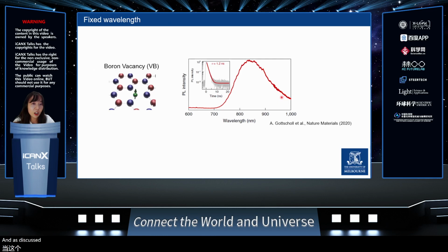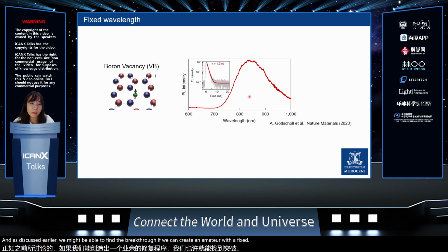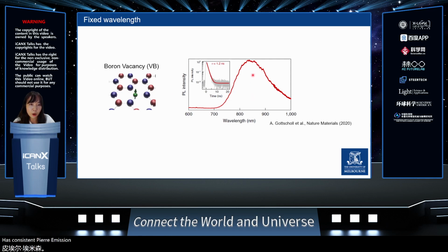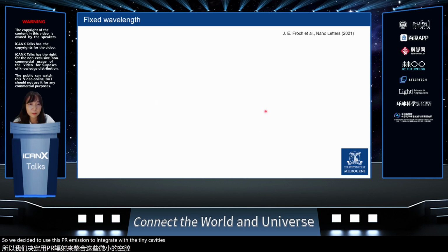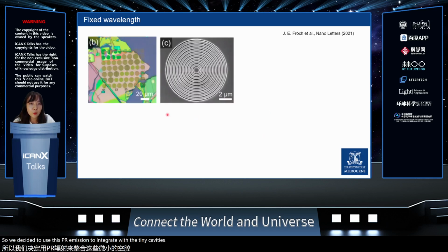As discussed earlier, we might find a breakthrough if we can create an emitter with a fixed wavelength. One of the discoveries in 2020 is that the boron vacancy in hBN has consistent PL emission around 800 nanometers. So we decided to use this PL emission to integrate with photonic cavities. In this work, bullseye cavities are patterned onto an hBN crystal. The left image is from optical microscopy, where you can see the hBN crystal here. The right one is an SEM image.